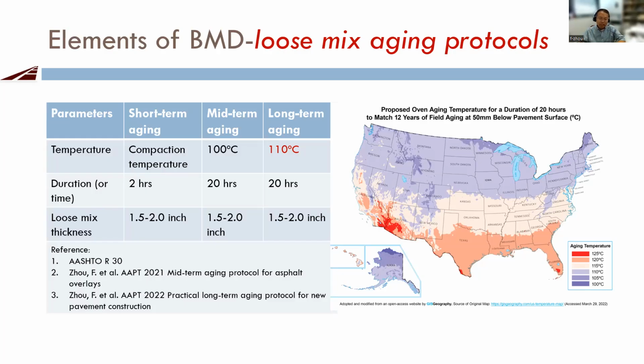And for the midterm aging, the only difference is the aging temperature, 100 degrees Celsius, and the duration is 20 hours, and the loose mix thickness is still 1.5 to 2 inches. For the long-term aging, we increase another 10 degrees Celsius. If you look here, we have a map, the national map.